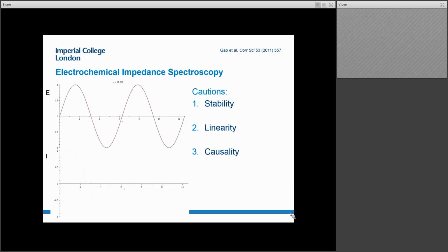So with that, you can see at the top, the red curve, which is nicely going along, is the applied potential. So it's a sinusoidal wave. And what we're doing is we're applying that and we're measuring the current. Sounds familiar. What's nice is we're looking for changes in amplitude, phase shift, and so on. So it's a perturbation technique. But what is different about this is we start at a high frequency, and then we work our way down to lower and lower frequencies.